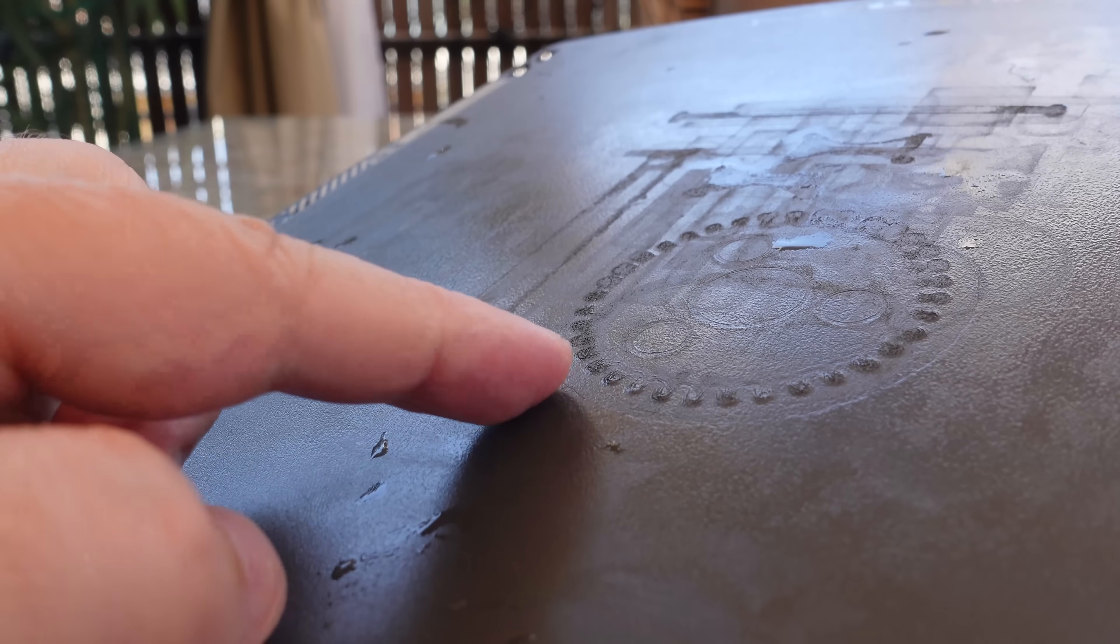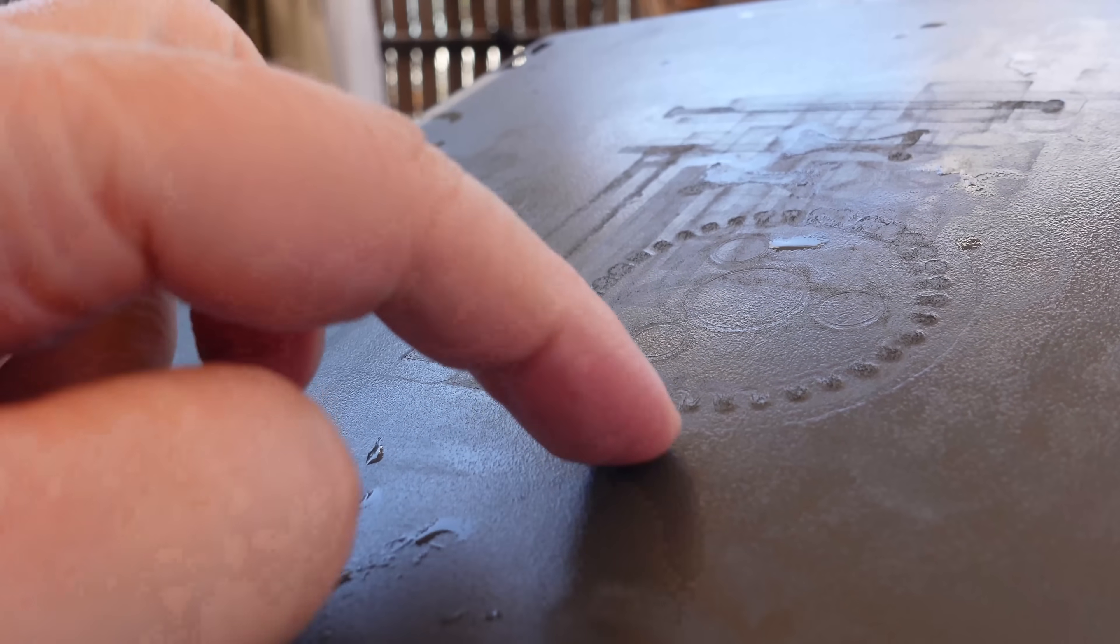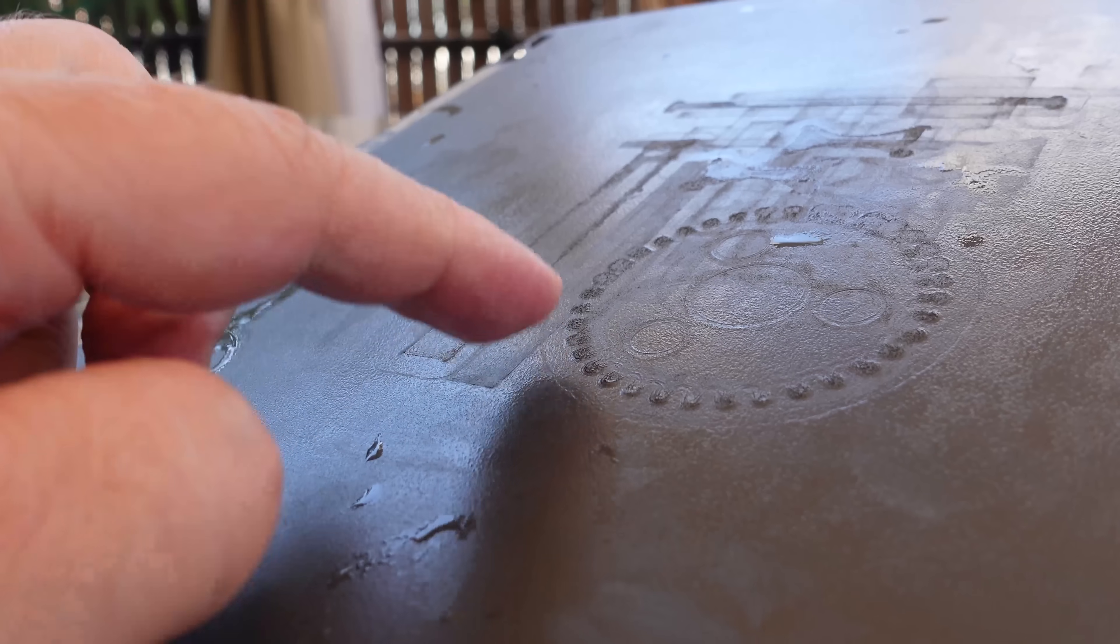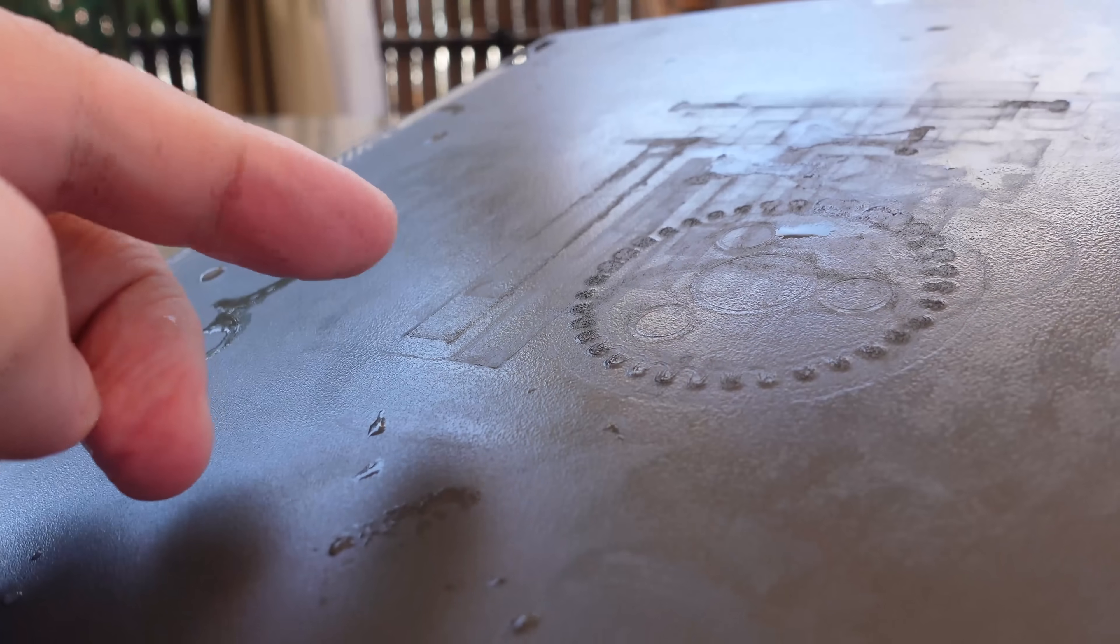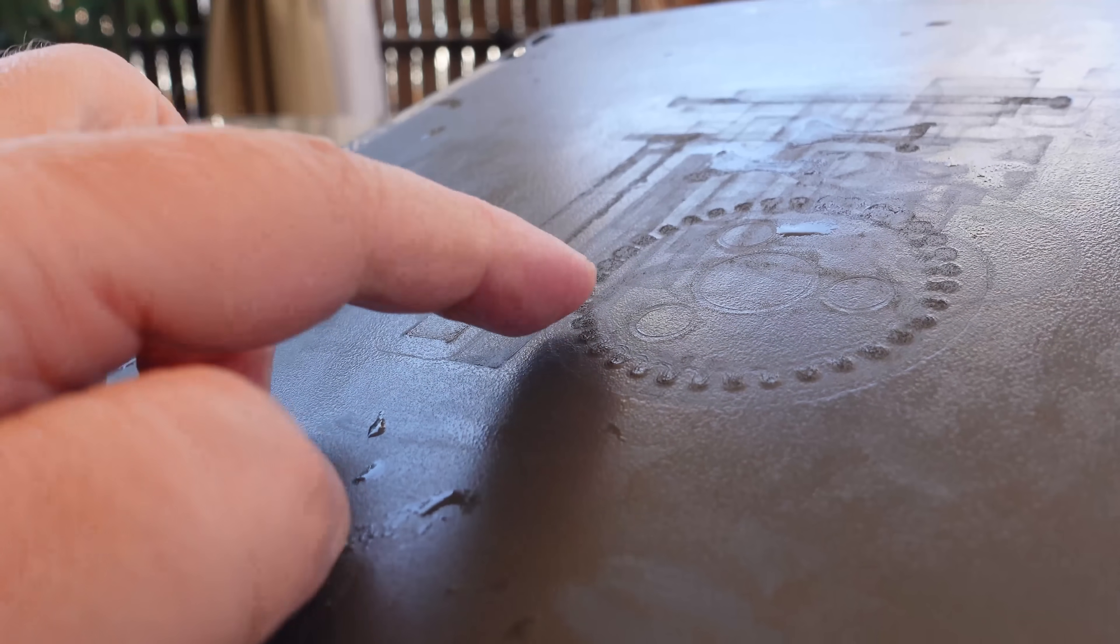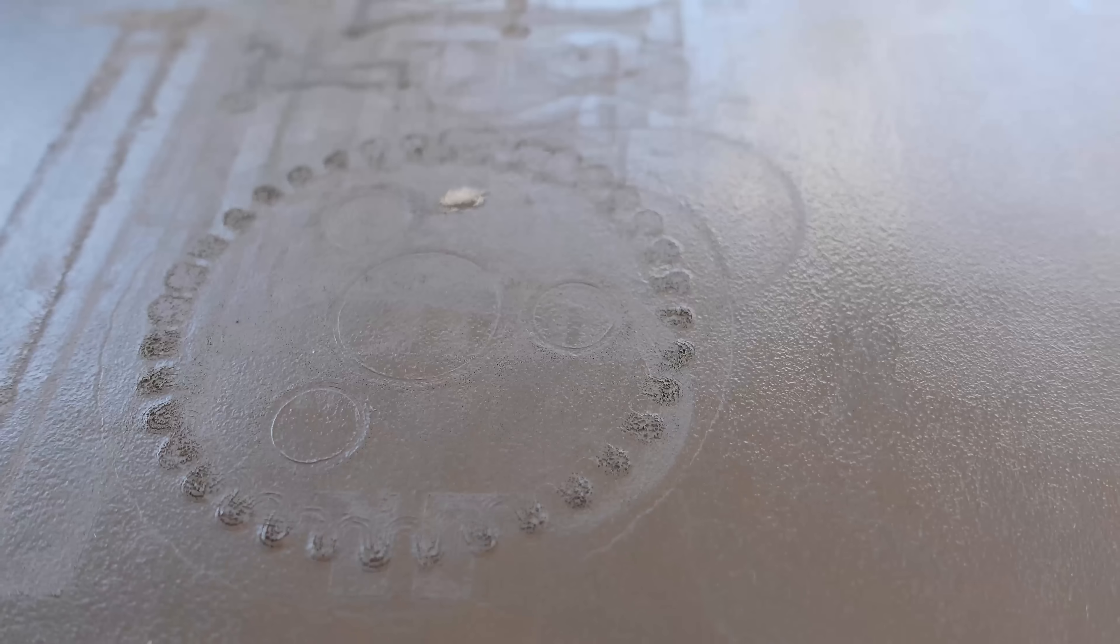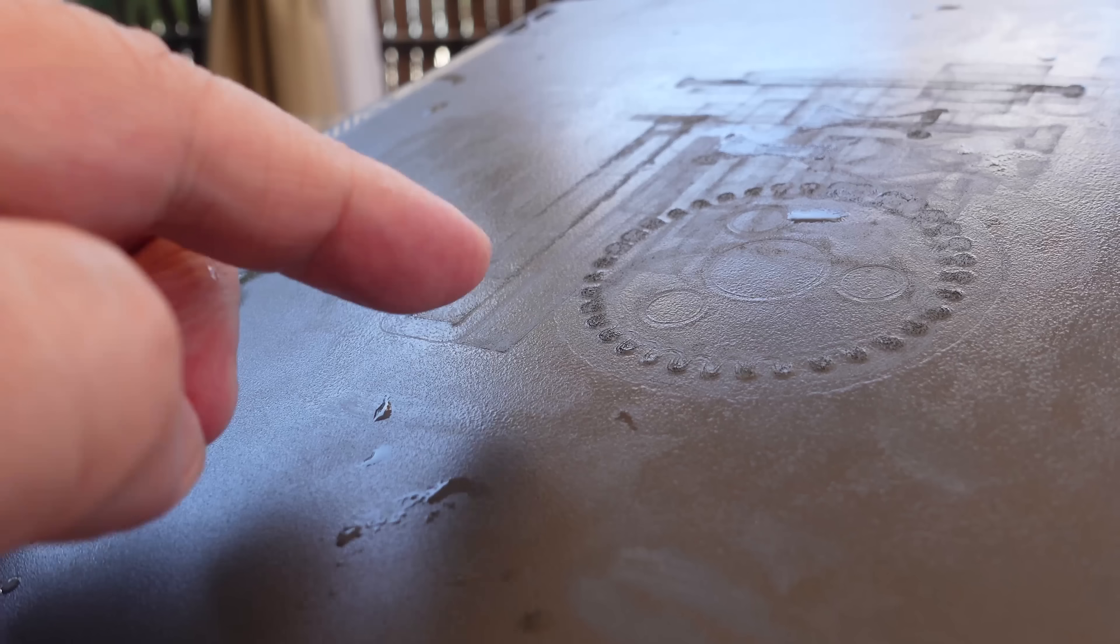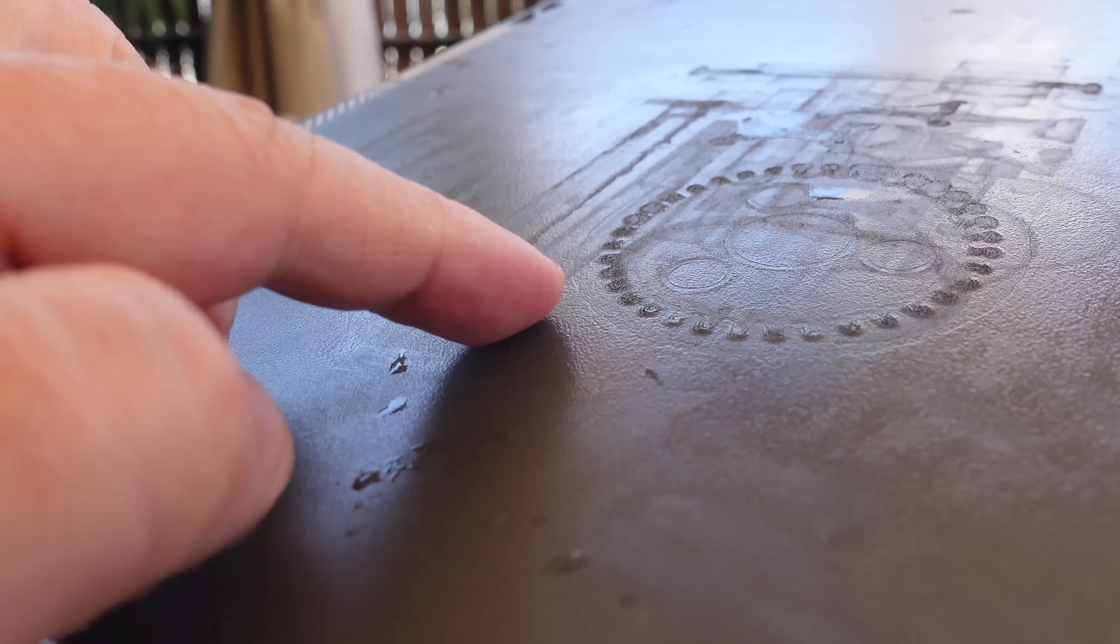I washed the engineering plate from the glue, and the first time I noticed this kind of errors on my X1 Carbon, it looks like the nozzle was too low and it damaged the surface. And this is also the first time I am preheating the bed to 110 degrees Celsius and I was waiting 20 minutes before the printing.